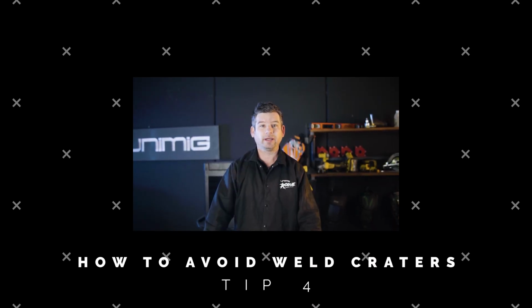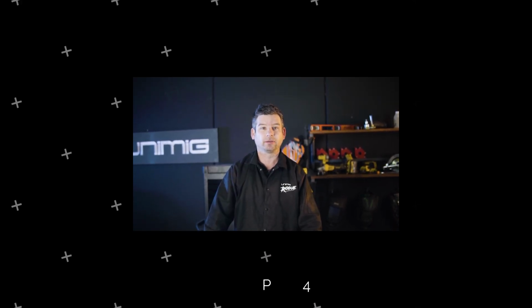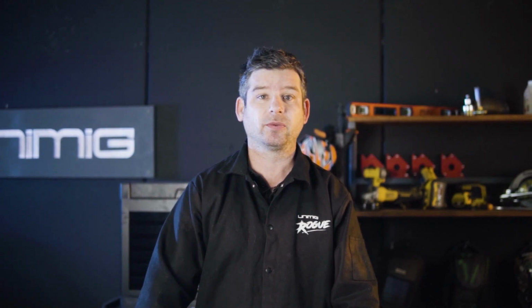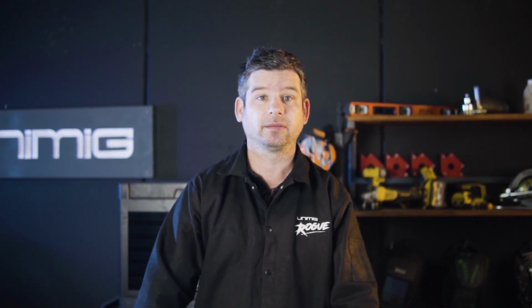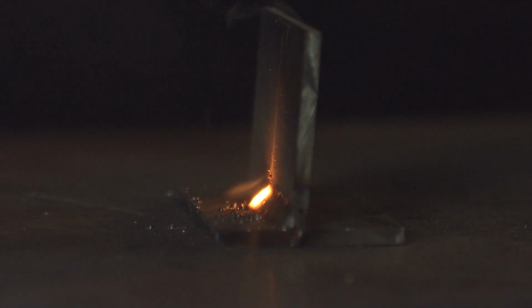Today we'll talk about weld craters and how to avoid them once you finish your weld. First and foremost, we recognise weld craters as a common weld defect. They are a weak point at the end of your weld that often results in the start of a crack as the metal cools. As a matter of fact, these craters occur because not enough filler metal was added to the end of the weld and the weld puddle wasn't reduced.